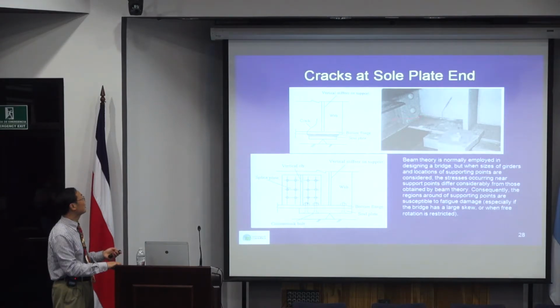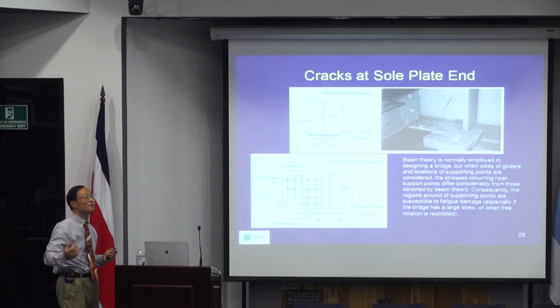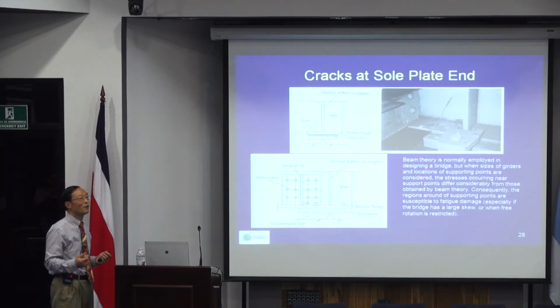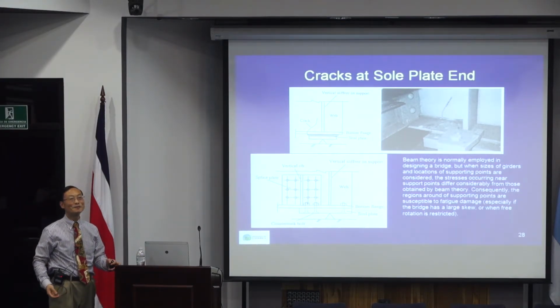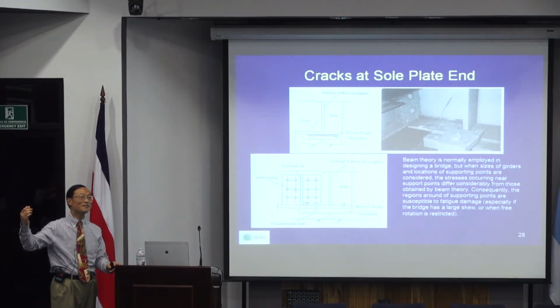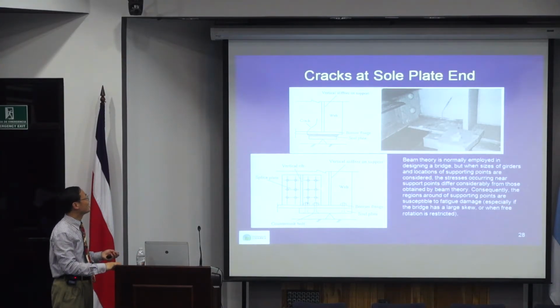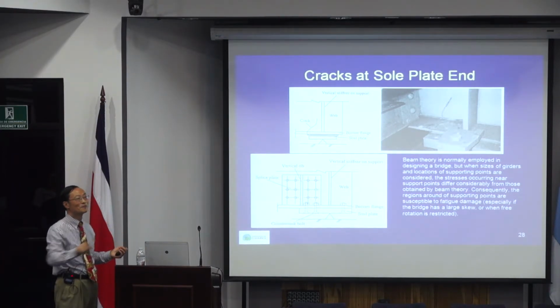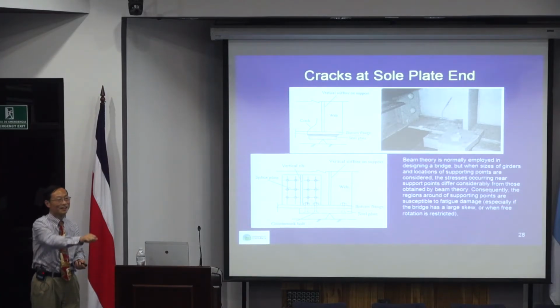That's also like for bearings. You assume it's a hinge, but in many cases the bearing becomes frozen, and you may develop cracks there. In that case, you just bolt two T sections to each side. And sometimes some people say, okay, before bolting these, I drill a hole at the end, then I bolt. That will be fine. Bolting plates is the most popular way to repair fatigue cracks. But the problem is when you bolt these, it's visible to the public. So if it's a very visible and very sensitive area, and people don't want to see that, then you cannot do that. In that case, you typically have to cut a V shape into these and provide a full penetration weld. We call it a V and weld. So first you cut a V shape and then weld into that.